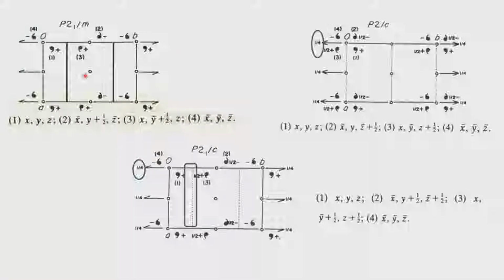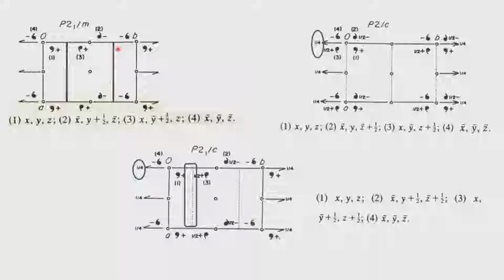In the symmetry diagram, therefore, we have the center of symmetry indicated at all the corners of the unit cell as well as at the half positions along A and B. The presence of the 2-1 axis is illustrated along the B direction and also at the cell edges, and also halfway distance along the A direction. And the mirror symmetry is now moved away from the origin, the intersection of the origin and the 2-1 screw axis, by 1/4. So, the mirror now appears at 1/4 and 3/4.